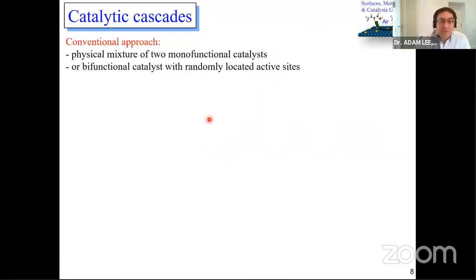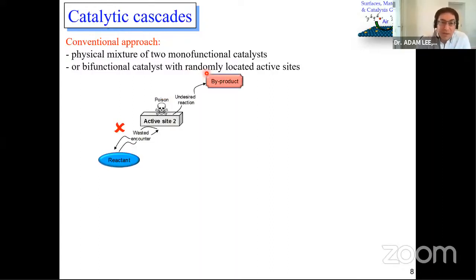Traditionally, we would simply take a physical mixture. We would take two individual catalysts and put them into the same reaction flask. Or we would take a catalyst support and we would randomly put these two elements into the catalyst. So we're not controlling the location of those. That's a problem. So for example, if we do those approaches, then we have to face the reality that the reactant molecule could go to the wrong active site first in a cascade. If it does that, the best case scenario is it simply bounces back in a wasted encounter. The worst case scenario is it could poison the catalyst or it could make the wrong molecule.